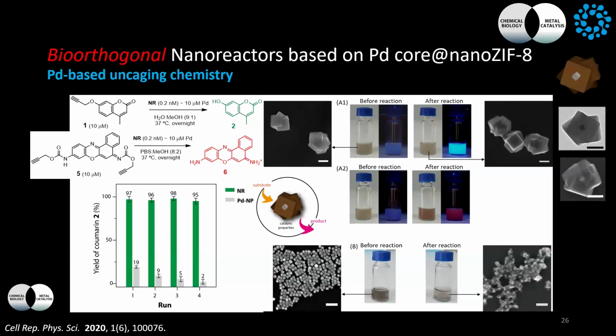Okay? So the idea was now, again, in collaboration with Jose Luis, he has these molecules that are fluorescent, but when you put a propargyl group on them, they become not fluorescent. Okay? And the idea was to have a heterogeneous palladium catalyst, more advanced than what they use in the lab to produce 2 and 6, which are simply fluorescent products. But these things, you can do also with molecules to become active or toxic or whatever. Okay? In our particular case, it's also true that this is toxic.